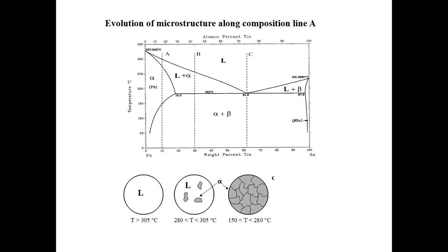Alpha is going to be... let me do this for you. So I choose 100 degrees, right? This is not a very low temperature. So I would say my alpha phase, we know that now we're going to have alpha plus beta coexistence. This is from the phase diagram, right? And I know that the alpha composition is going to be roughly 5%, probably 6 or 5. And the beta is going to be 98, probably 98, 99%, right?